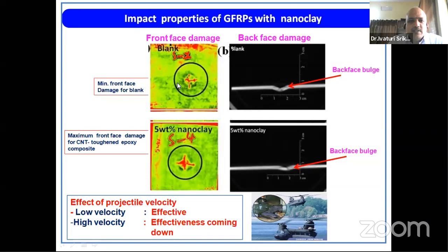What happens is, if the front face damage is maximum, then most of the energy is consumed in generating the front face damage. And by the time the impact load moves to the rear side of the composite, the damage will be minimum, because most of the impact energy is already consumed in generating the damage on the frontal side.